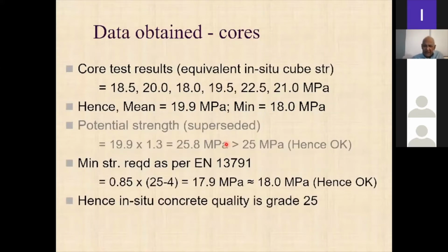So I had to advise the person concerned to go for core tests. He had taken many core tests, maybe more than is required. So all of these you get from the cores. The mean you get is 19.9 MPa and the minimum is 18.0. Now this is, of course, if you are using potential strength, which is superseded. If you are using that, you take this multiplied by 1.3, giving 25.8, greater than 25, hence okay, right? Now, if you take the minimum strength required as per this EN, you take 25 minus 4 times 0.85, that is 17.9, right?